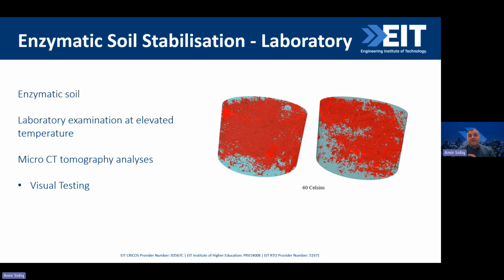And if we go to 60 degrees, and 60 degrees is pretty high for soil, we can see the void for the raw material is going pretty high, but for the enzymatic, it's almost remained the same. Now, sometimes I call this a smart additive, because it's actually controlling the clay particles according to the temperature. At the low temperature, there is slightly high porosity because we need to allow the expansions. At the high temperatures, there is still a particular void content, again, to protect it from the shrinkage. So it's protecting it from the swelling and protecting it from the shrinkage, keeping the sample almost consistent throughout the different temperatures. This is only some visual testing, but you can clearly see the differences.